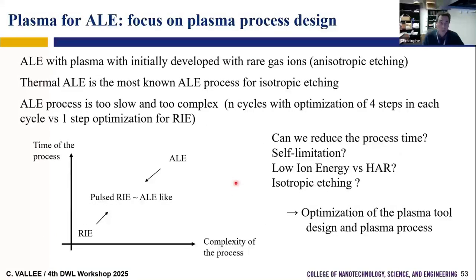Regarding the semiconductor industry, we use more and more ALE, but ALE is more complex to develop, because an ALE is a sum of 4 steps, and we have n cycles. So it means that to optimize your ALE process, you need to optimize all the steps and the cycles, while it's only 1 step of optimization for RIE. And ALE is very slow. So it means that the throughput is not good enough.